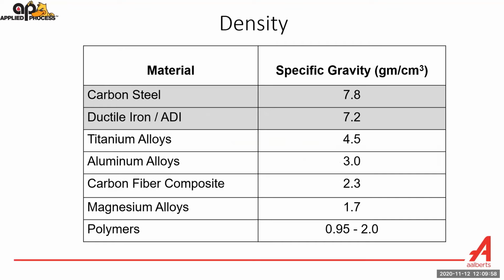The other nice thing about ductile iron and ADI is by switching your part maybe from carbon steel to ductile iron or ADI, you get an immediate approximately 10% reduction in weight, and that's due to the graphite nodules that are in the part.